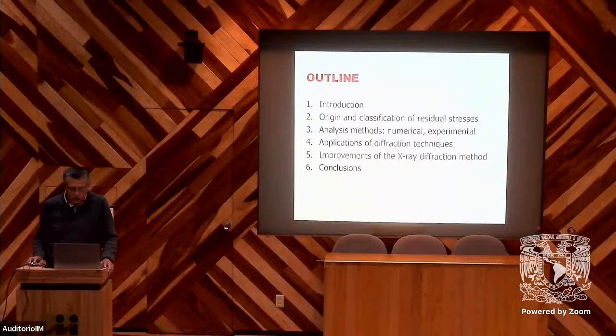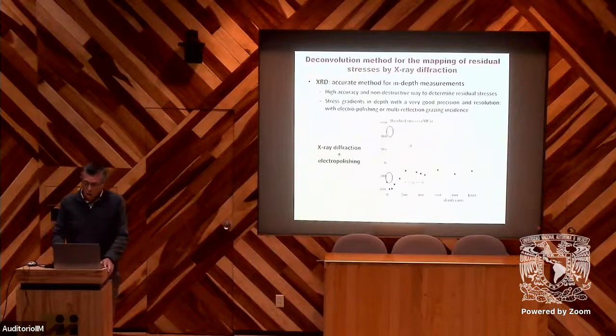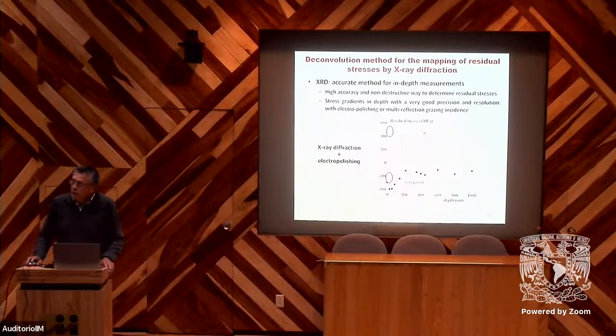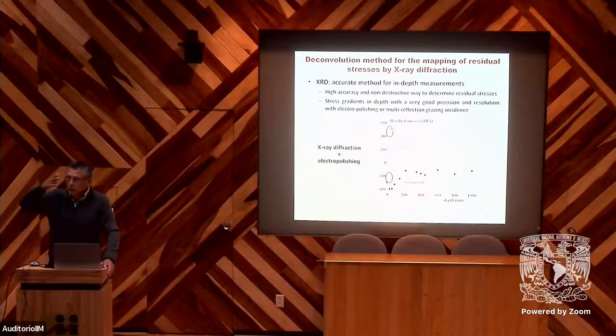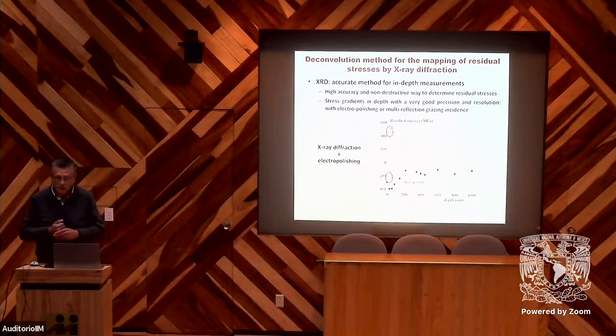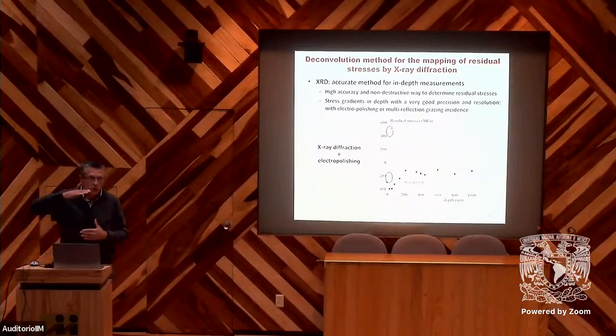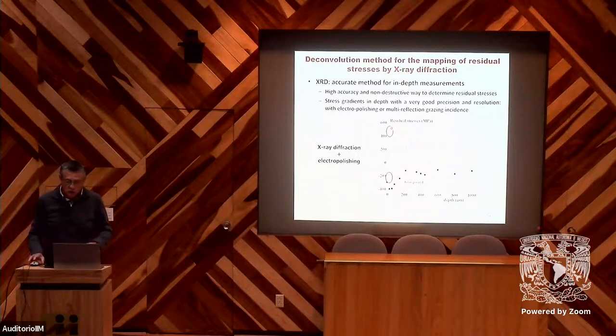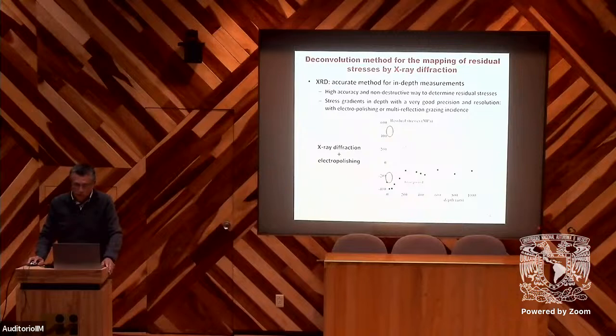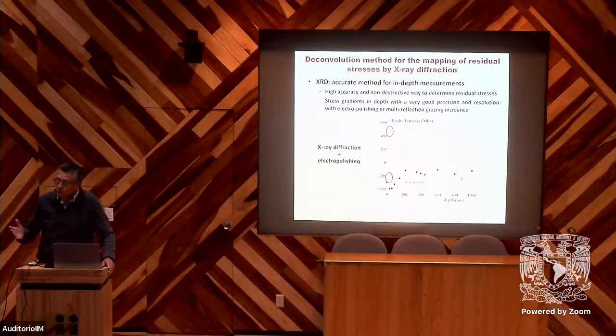Now, before the conclusion, I would like to present to you a new development of a classical X-ray diffraction method. We have this classical method that gives the possibility to have the in-depth distribution of residual stresses using diffraction and electropolishing. We remove layers and measure, so we can get the repartition of residual stresses between the surface and in depth. We can reach, for example, in general, 0.5 millimeter, but in some cases we can go to 1 millimeter, not more. And this is the profile for as-machined, and this is after laser cleaning.